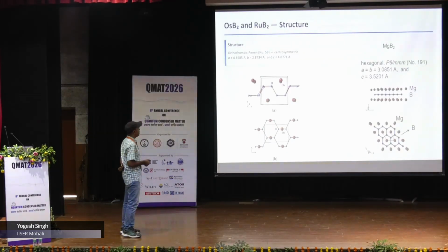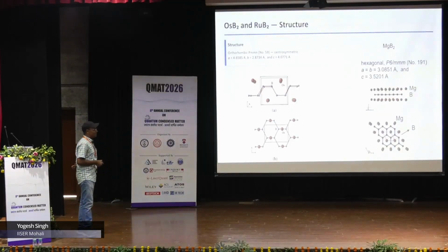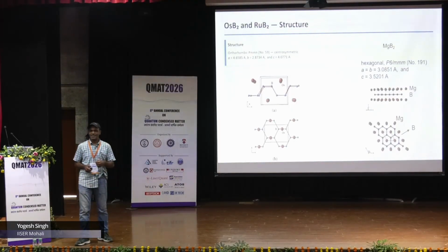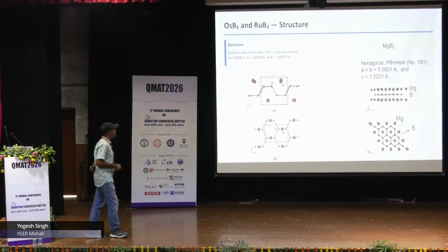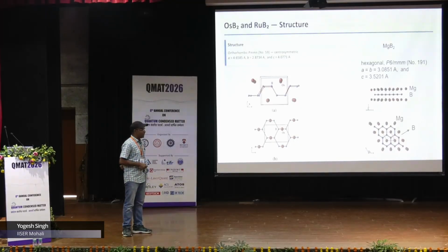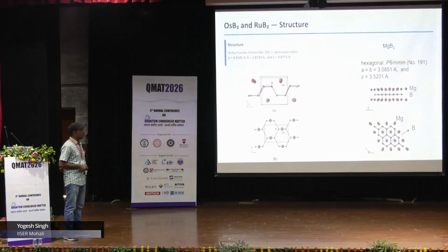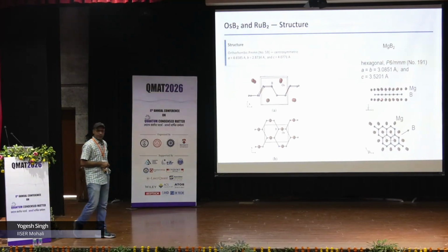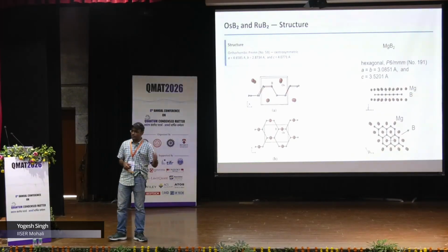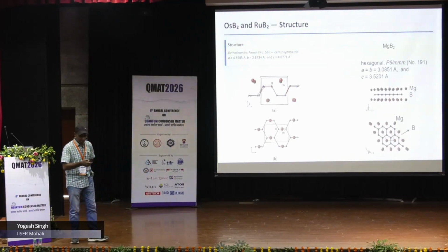Okay, so this is the crystal structure. This is also an example of how science progresses non-linearly. When we started this in 2006, the motivation was to try to find another high temperature superconductor like MgB2. MgB2, of course, has a famous boron honeycomb lattice. In these materials, if you look down the c-axis, we have a boron honeycomb lattice, but it is warped in the third direction. And therefore, we were looking at some similarities with MgB2 and trying to see if we could get a superconductor.